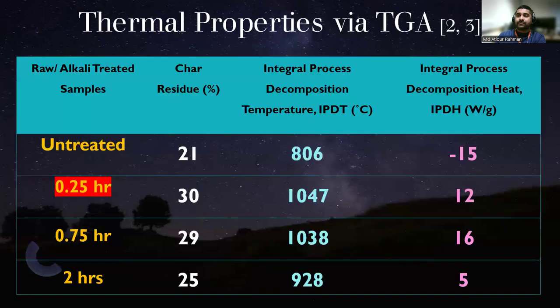Let's see what properties we got. So we got the untreated. When we have the untreated fiber, the char residue, we got 21%. I should mention that all these tests have been done maintaining the industry standard. And for this one, the heating rate, we used 10 degrees centigrade per minute, and under the nitrogen atmosphere, the nitrogen was, if I'm not wrong, 110 milliliters. So taking back to this one, the untreated fiber got 21% residue, whereas for all the treated, it's actually enhanced.